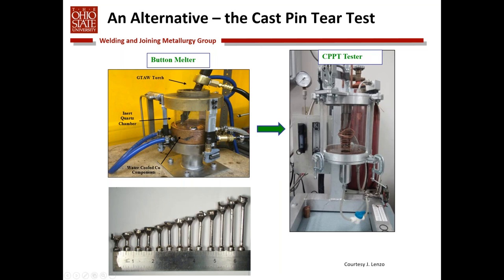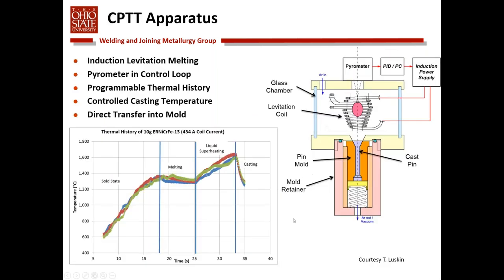And what happens, not surprisingly, as the pin gets longer, under solidification conditions the strain that builds up during solidification increases. And at some point in time, you'll tend to get a crack in these pins. Sometimes the entire head of the pin will come off, but you'll get some cracking in the pin itself. This is how the test is run. Basically, we put this small button into a levitation melting coil.